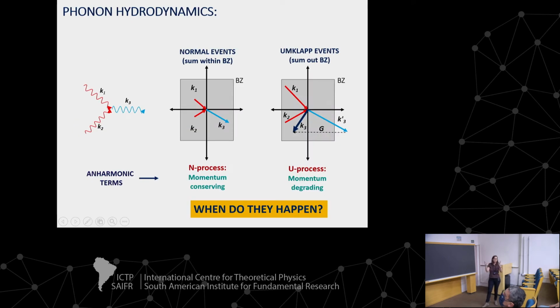Just to picture that in a very simple way, if we consider a 3 phonon scattering, the normal events are the ones that show a sum that falls inside the first Brillouin zone. Therefore, they conserve energy and momentum, and we don't have momentum degradation. On the contrary, when the sum of 2 phonons goes out of the first Brillouin zone, then we can go back by a reciprocal lattice vector, and therefore we have a vector that points in that direction, so we are losing, in fact, momentum. This is what we call N process and U process.